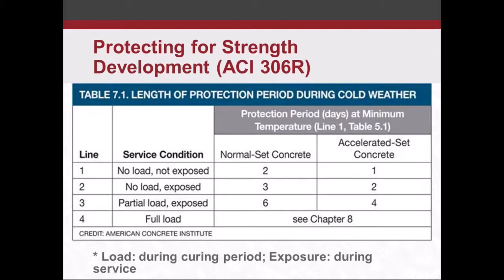What we've got over here are service conditions on the left, and then on the right we've got protection period depending on whether our concrete is normal set concrete or accelerated set concrete, where we're using an accelerator, non-chloride accelerators, right? We can shorten our protection period a little bit. Up here it says protection period at minimum temperature, line 1 from table 5.1. That line 1 is the 55 degrees for our sections less than 12 inches, or 50 degrees for those sections between 12 and 36 inches.